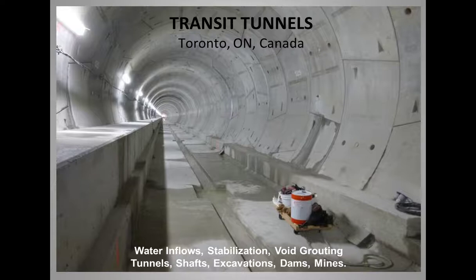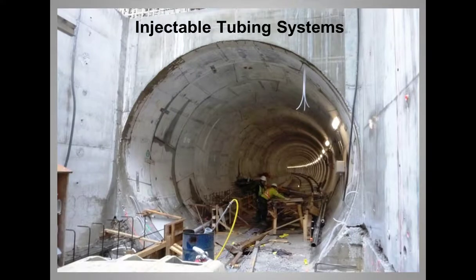Leaks were observed infiltrating between the precast segments themselves. These leak locations were repaired by drilling and injecting through the segments with water-activated polyurethane. A highly expansive, quick setting, semi-rigid product was selected for this project to account for the movement of the concrete due to Canada's harsh climate. Single component water-activated polyurethane can be easily adjusted on site by changing the dosage of the activator component to solve minor, moderate and severe leaks.